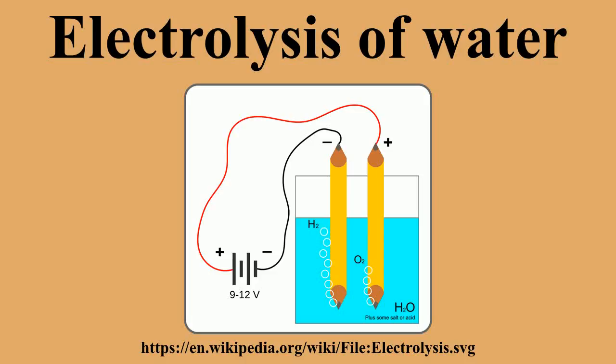Care must be taken in choosing an electrolyte, since an anion from the electrolyte is in competition with the hydroxide ions to give up an electron. An electrolyte anion with less standard electrode potential than hydroxide will be oxidized instead of the hydroxide, and no oxygen gas will be produced. A cation with a greater standard electrode potential than a hydrogen ion will be reduced in its stead, and no hydrogen gas will be produced.